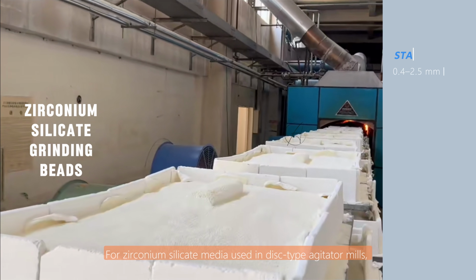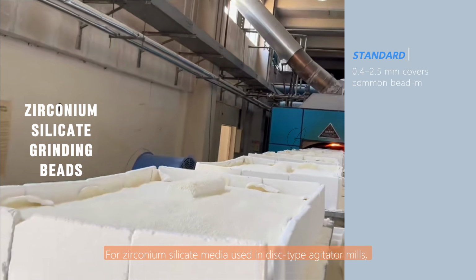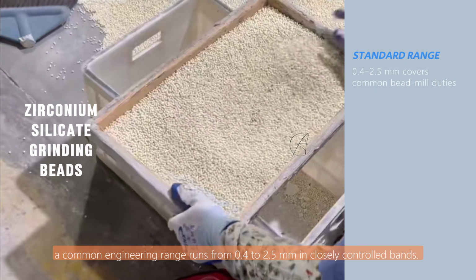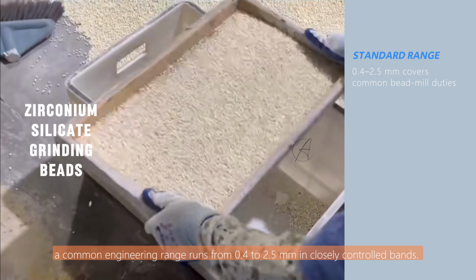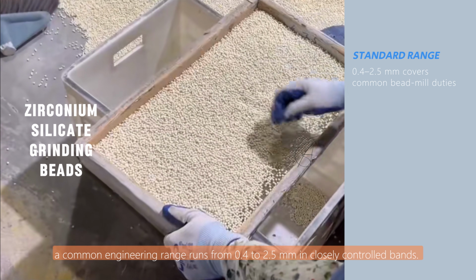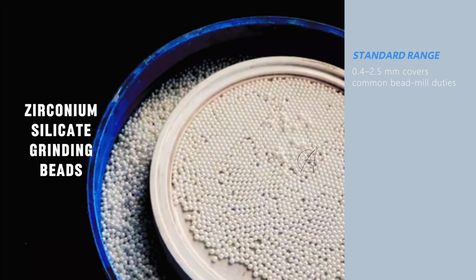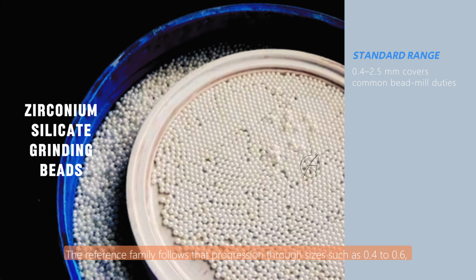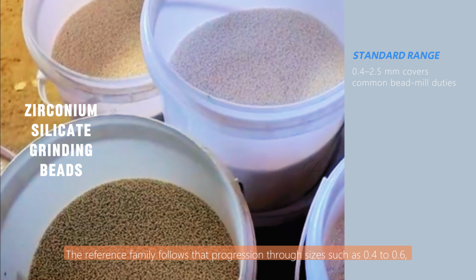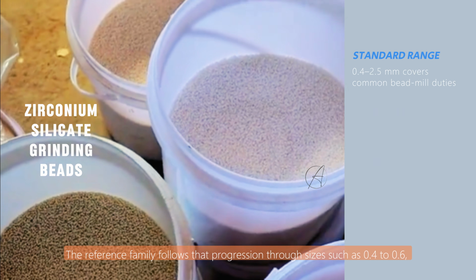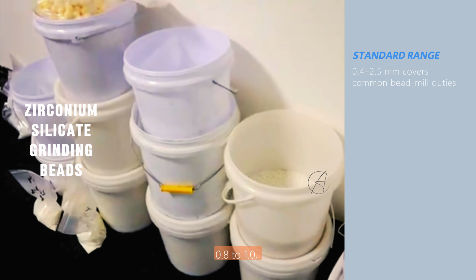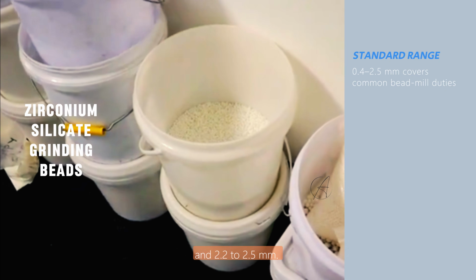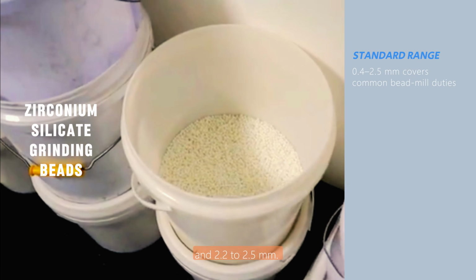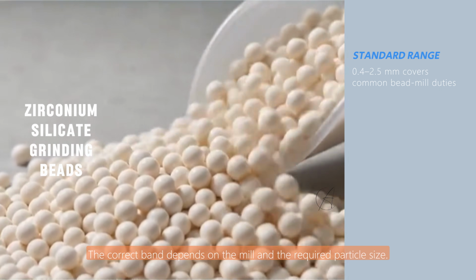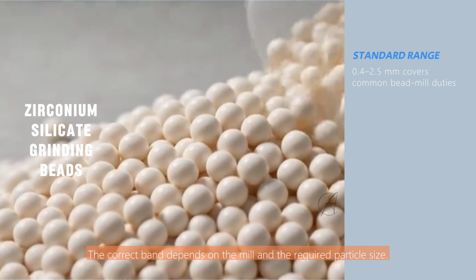For zirconium silicate media used in disc-type agitator mills, a common engineering range runs from 0.4 to 2.5 mm in closely controlled bands. The reference family follows that progression through sizes such as 0.4 to 0.6, 0.8 to 1.0, and 2.2 to 2.5 mm. The correct band depends on the mill and the required particle size.